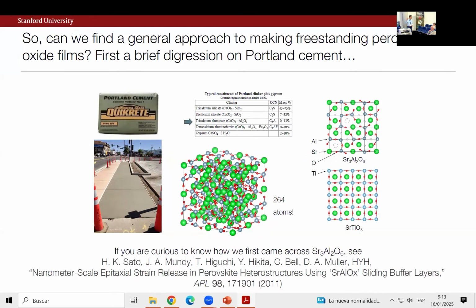But if you go back, I think, to the 1950s, where this structure was first refined, I think it was labeled in some cases a pseudo-perovskite, as I'll show you. And one of the ways you can already see this is that if I take a slice of this, a quarter of this unit cell in one direction, you can immediately see something interesting. If I put this with respect to 4 unit cell by 4 unit cell building block of strontium titanate in the 100 direction, you can see there's a fairly good correspondence, and there's something better than a 1% lattice mismatch between the two. So somehow this structure is almost like an ordered array of both cation and oxygen displacements or vacancies in this lattice.